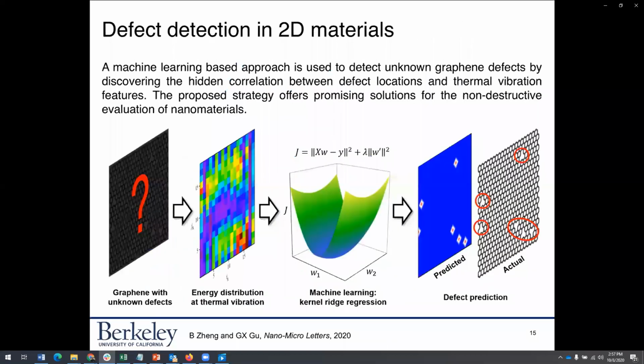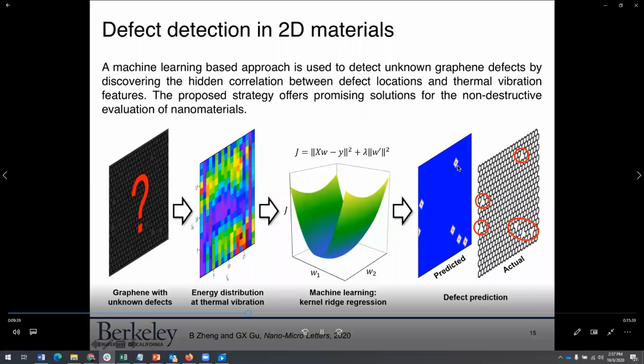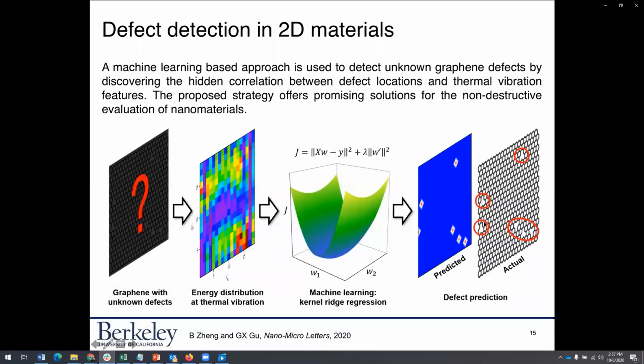Here we have also looked into how we can detect defects in graphene. Let's just say we have a graphene with unknown defects shown here. By training a model with computed thermal vibration features, we're actually able to predict. So this is predicted and this is the actual graphene with different locations for defects. We're able to predict with a trained model where these defects are actually located. And so a machine learning based approach is used to detect unknown graphene defects here by discovering the hidden correlation between defect location and thermal vibration features. The proposed strategy, we believe, offers promising solutions for non-destructive evaluation of nanomaterials.